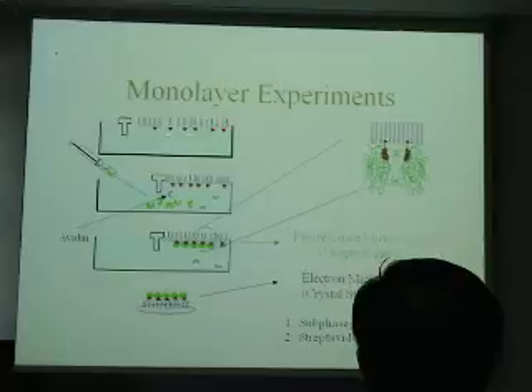So what we do is quite simple to draw, and of course difficult to do, because surface science is always fairly challenging. But we take a monolayer of lipid, put in 1/10 biotinylated lipid, compress to the desired surface pressure, put the protein in the subphase, it attaches to the lipid membrane, and then forms crystals. So if you look at a drawing to scale, you would see streptavidin here with a number of lipids above it, about 40 lipids per streptavidin molecule by area. And 2 of them will have biotin and be attached to the streptavidin.